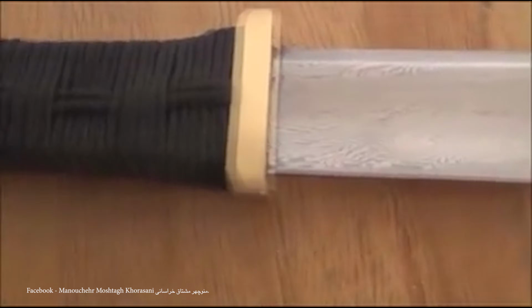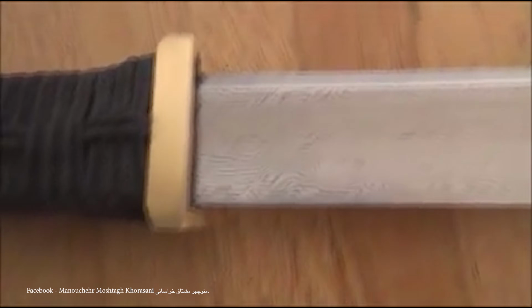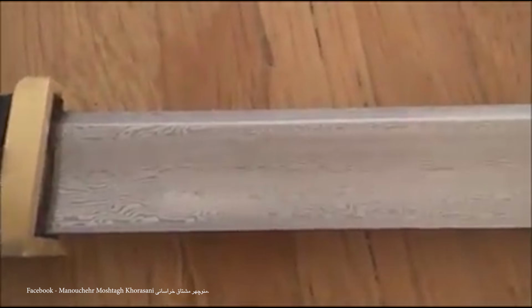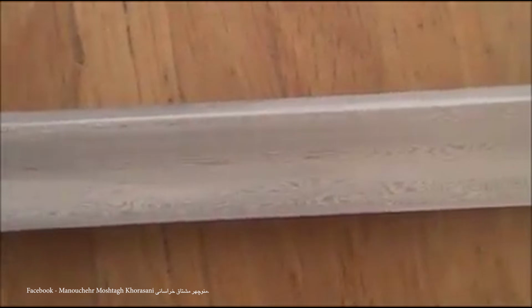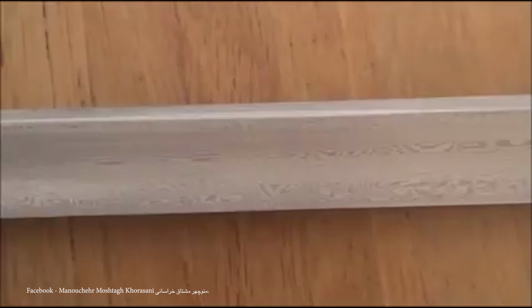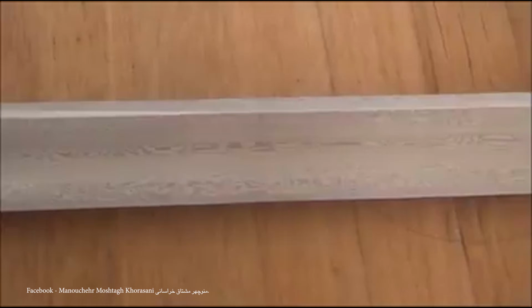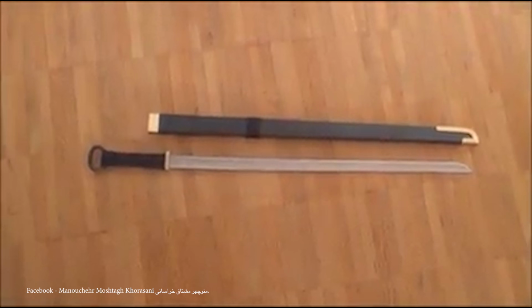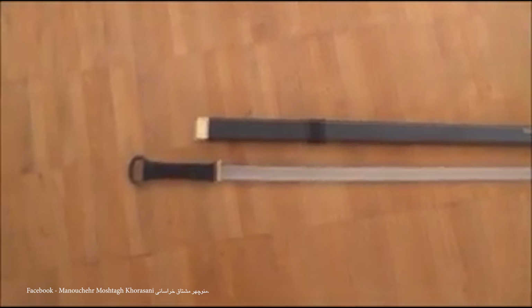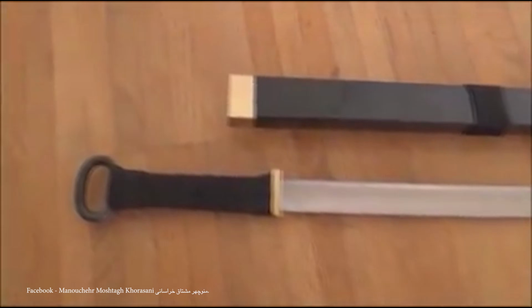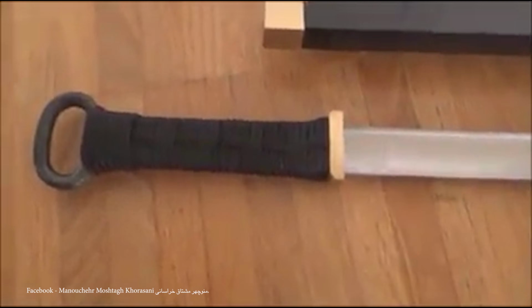Song Dao typically measured 70 to 90 centimeters and featured a curved, single-edged blade with a strong spine. Many excavated examples show differential heat treatment, with hardened edges and softer, more flexible backings. Metallurgical studies confirm that Song smiths practiced forge welding of layered steels, resulting in blades with high durability and cutting power.